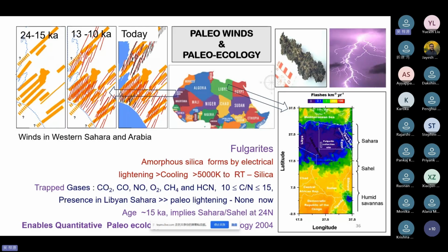The next is the fulgurites, which are the materials produced by the strike of lightning, where lots of energy is being deposited and temperatures up to 30,000 degrees Kelvin can be raised. When this happens, the material where it strikes melts and captures all around it and keeps it safe for a long time. It's a glass now, and it looks like a root-like structure.